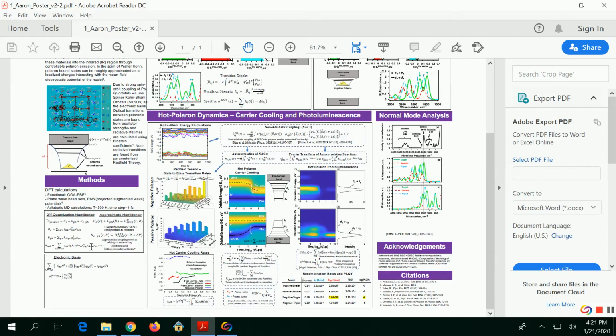To approximate that in DFT, essentially we compute an N electron system as the ground state, and then we either add or remove charges and let the model re-optimize. We approximate that as the electron-phonon coupling, so it's an approximation for the polaron binding energy. So the polaron energy equals H_e plus H_ph plus H_e-ph. Is that a citation? Yes.